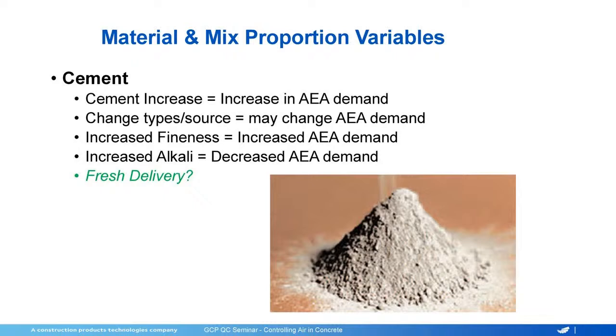The other thing is the temperature can be when the mills are running at capacity. You may be getting cement that's not sitting in a silo for any length of time, and the temperature could be a bit higher. And if the temperature is higher, it's going to cause you to need more air in the concrete. We had a customer some years ago now that was getting cement. They were already in the hot weather market, and we ended up putting about 5 gallons of air in a 3-yard batch at a precast plant to get air. And it was just because the cement was coming in at a fairly high temperature, which 5 gallons of air, that falls under the category of that would scare the crap out of you to use that much air in your concrete. If things go back the other way, you're going to have a lot of air. So yes, when you're chasing air issues, when you're trying to control air, anything that's different should be noted.